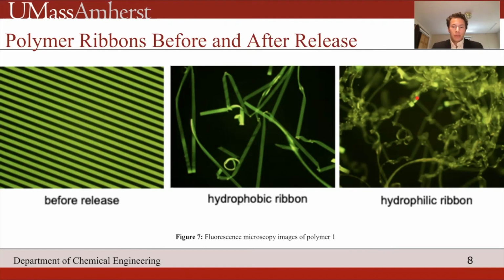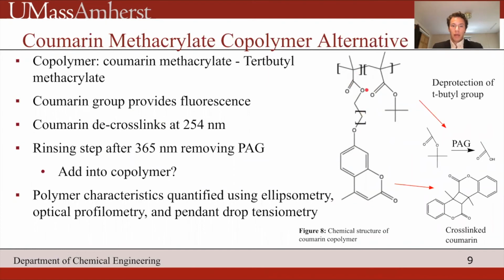However, one problem that we were seeing with this polymer was leaching of the fluorescence into the solution. And so we decided to try a new polymer, a copolymer of coumarin methacrylate and tertbutyl methacrylate, because coumarin, which is the cross-linker group, is also fluorescent, and so the fluorescent group can't be completely removed from the polymer, so it would no longer be leaching. And so this is the coumarin methacrylate, tertbutyl methacrylate copolymer. Again, tertbutyl methacrylate is used because after deprotection using PAG at 254 nanometers, it's able to change the deprotected part of the polymer from hydrophobic to hydrophilic. And coumarin cross-links at 365 nanometers to form this cross-linked version of coumarin, and in doing so is also fluorescent and is therefore able to be visualized under optical microscopy.